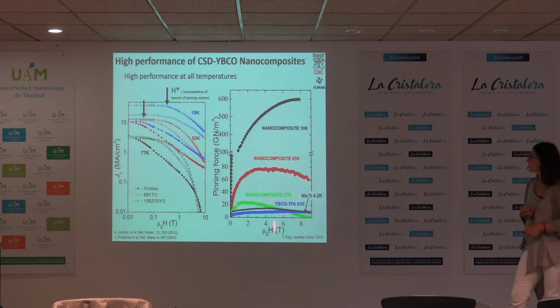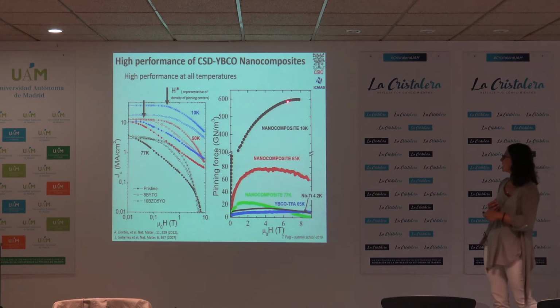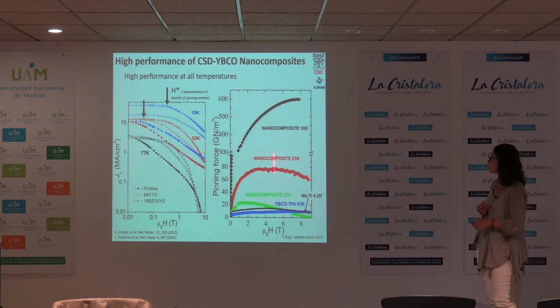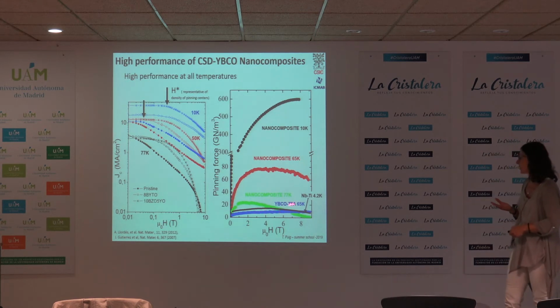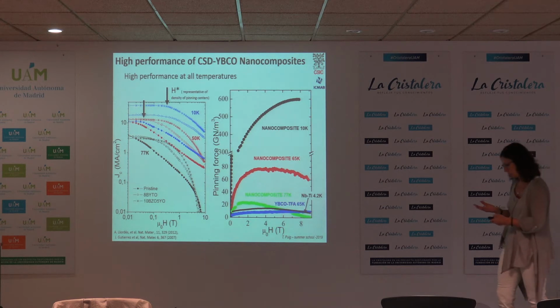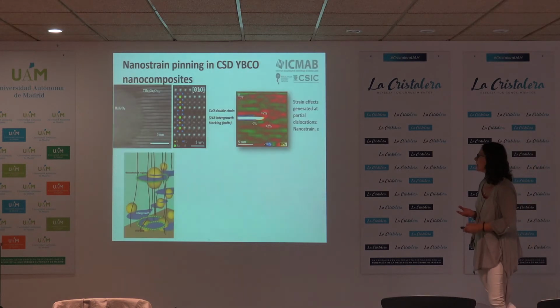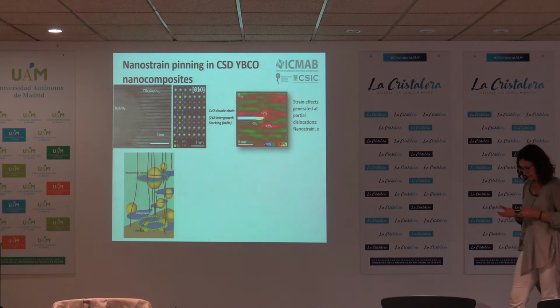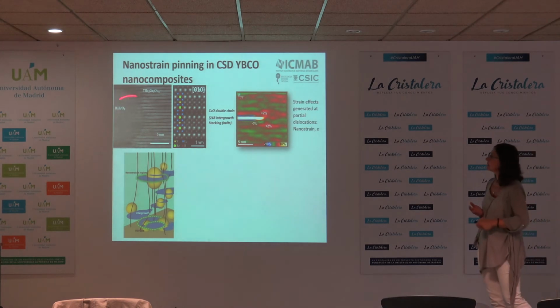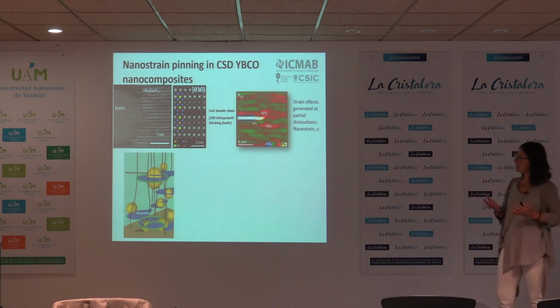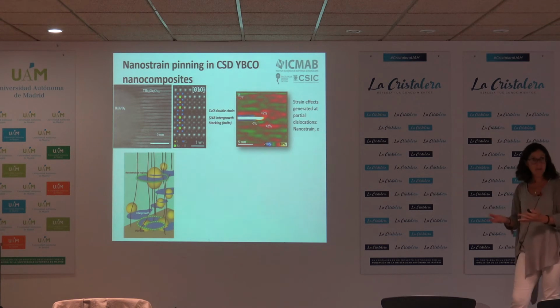And again, we see that the pinning forces of these CSD nanocomposites also increase a lot when compared to the standard YBCO without nanocomposite or also with a niobium titanium. Now, in this case, what we in fact see is that these random nanoparticles generate a lot of defects into the matrix of the YBCO.